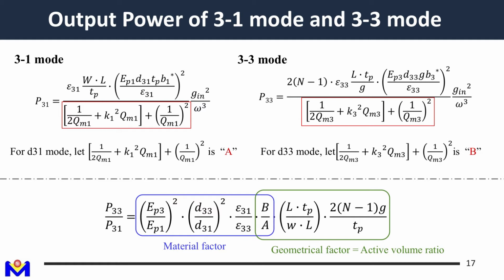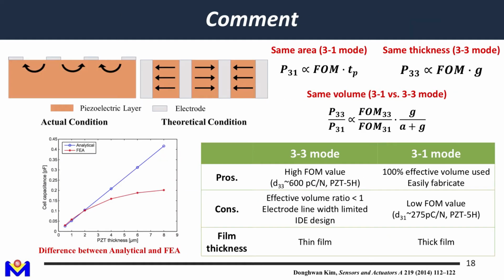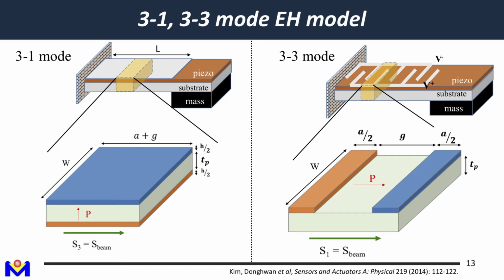And also from this formula for the geometry factor, we can have another simplification. This term actually depends on the total effective volume of the piezoelectric layer. For example, here, this is the 3-3 mode. We should go back to here. I'm sorry. I mean, for effective volume, if we can have a thinner piezoelectric film and thinner substrate, that means we have a larger effective piezoelectric material, and of course the output will be larger.